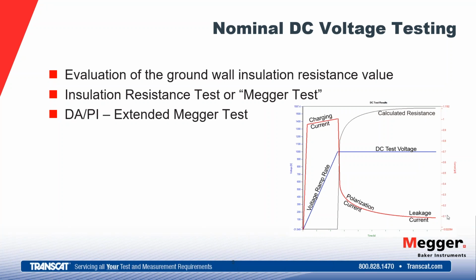And then we're going to read the current value at the end of 1 minute. We know the voltage, so we're going to take the voltage divided by our current and arrive at the resistance value. And then we're going to temperature correct that value so that we can compare it to a minimum value. So again, this test itself lasts for a minute, and if we were to hold voltage on and continue the test after that 1 minute, then we move into the DA or the PI, which is basically an extended Megger test.